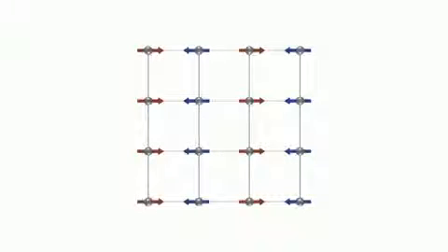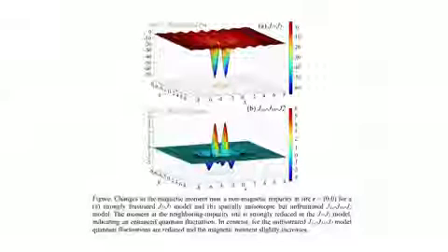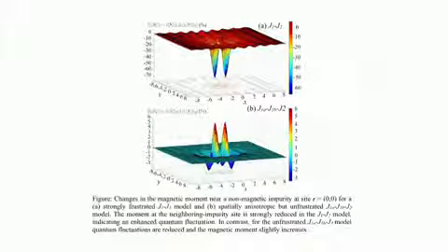Here we explore the possibility of probing frustration by the response of host materials to non-magnetic impurities, such as zinc substitution or iron vacancy. In particular, we investigate how local magnetic moments near impurities are affected. We find that in the frustrated J1, J2 model, a non-magnetic impurity induces strong quantum fluctuation and results in substantially reduced magnetic moments. In contrast, the anisotropic J1A, J1B, J2 model shows enhanced local moments near the impurity site.